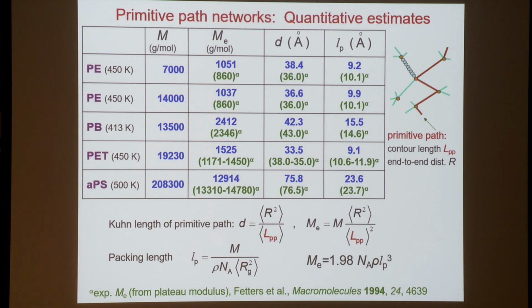Also, the last column contains what is called the packing length. This is a measure of how fat the chain is in relation to how stiff it is. It is calculated from the molecular weight, the mass density, and the mean squared radius of gyration. And we see that that too is quite well captured, which means that the simulation results confirm an empirically proposed correlation between the molecular weight between entanglements, the density, and the packing length to the 3rd power.